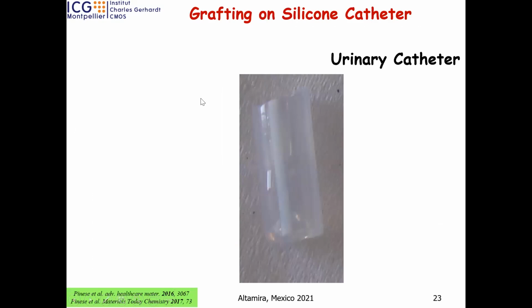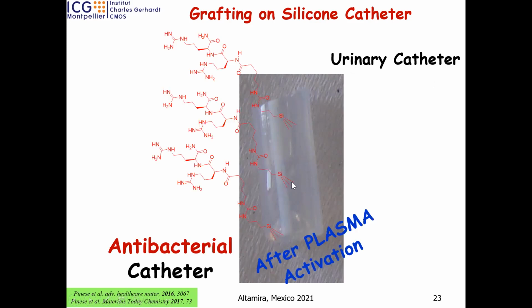Another example of grafting. Now we change the nature of the substrate. The first one was silica, then titanium, and now silicone. Silicone for me, it's PDMS. It's nice. We took a catheter made from PDMS. You take it directly from the pharmacy, and the idea is to immobilize peptide on the surface.